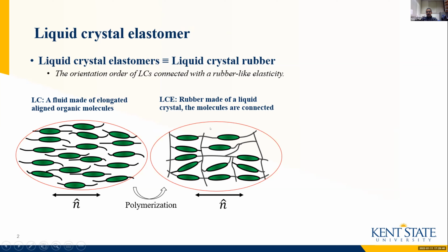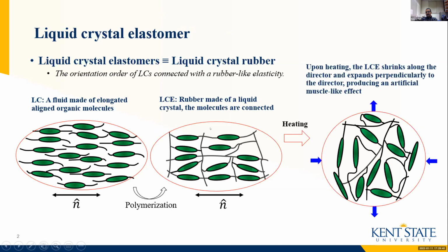Now, if you have a liquid crystal elastomer and if we heat it, upon heating, along the director it actually shrinks, and perpendicular to the director, it expands. So it produces an artificial muscle-like effect. To be noted here, in this polymer network, molecules are connected at both ends.